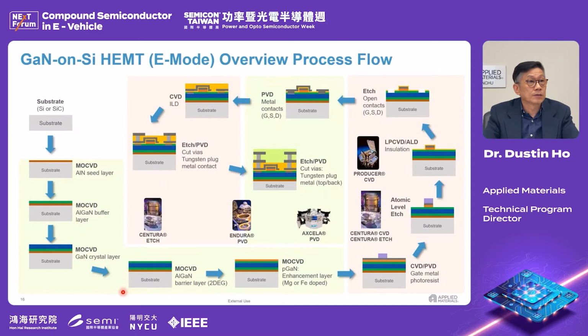Here is the typical GaN on silicon normally-off HEMT process flow. The substrate can be silicon or silicon carbide, then MOCVD, where you need an aluminum nitride seed layer and the buffer layer, and then the GaN layer. And then you need AlGaN for the 2DEG, and then you have another GaN. Then you need to do the etch. Then CVD for the gate metal photoresist, and then you have the ALE to remove the GaN, but you need to not damage the AlGaN area. So this is very critical for high selectivity.